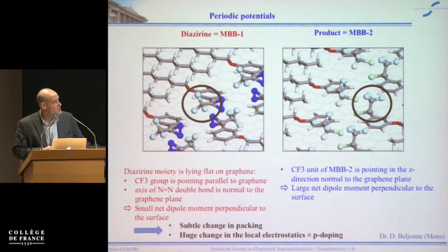Essentially, the major difference that you have in the two systems, MBB-1 and MBB-2, is this CF3 groups that, in the case of diazirine, is pointing parallel to the basal plane of the graphene. And therefore, what you have is a small net dipole moment perpendicular to the surface, whereas in the case of the product, this group is pointing up to the surface, so there's a large net dipole moment that is perpendicular to the surface.